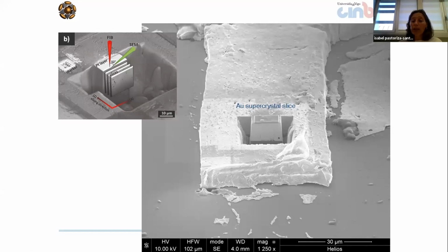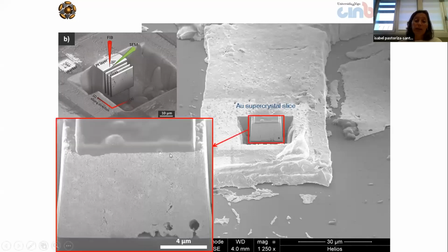And first we cut a supercrystal slice. This is the zoom of the slice, and then we perform a sequential milling with the FIB. And after each milling step, we took a SEM image. After finishing the milling, we took all the 2D SEM images, and we make a 3D reconstruction using Slice and View software.